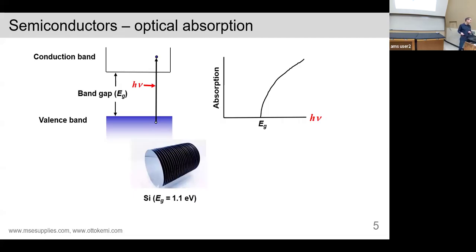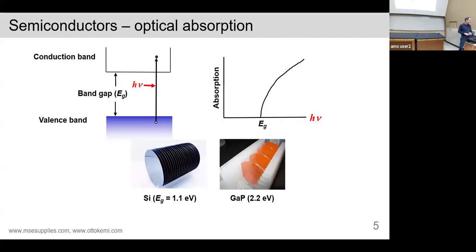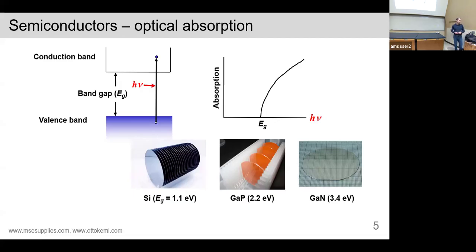1 electron volt, and so you can't see through it. That's in the infrared. Gallium phosphide has 2.2, which is in the reddish orangish part of the spectrum, and so it has that reddish orange color, but blue and green are absorbed, and so that's why gallium phosphide has that orange color. And then gallium nitride, it has a band gap in the ultraviolet, so it's transparent. Whatever color you see is due to defects.